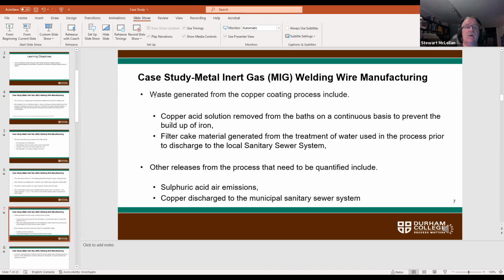Okay. Waste generated from the copper coating process includes copper acid solution removed from the baths on a continuous basis to prevent the buildup of iron. So as I had mentioned, it's a conversion process. The copper essentially replaces iron on the surface of the wire. So that wire ends up in the coating bath and has to be removed. It actually gets removed as a sludge from the bottom of the tank. The wastes also include filter cake material generated from the treatment of water used in the process prior to discharge to the local sanitary sewer system, right? So those are 2 wastes that need to be characterized for disposal under Ontario Regulation 347.